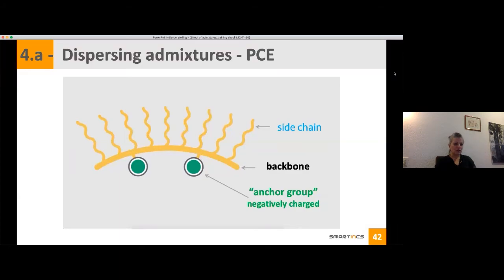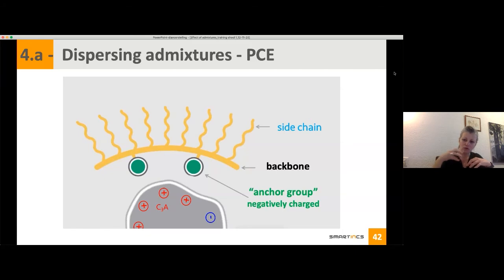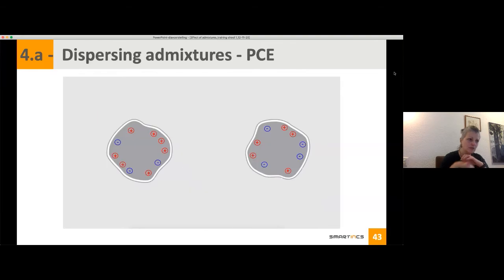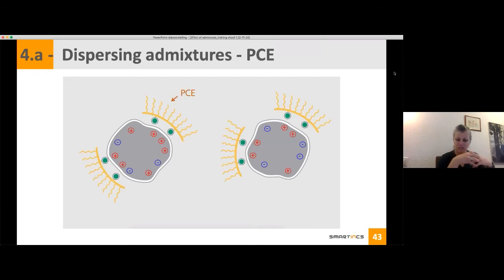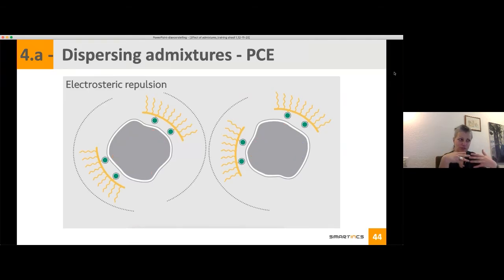So this is my PCE. If you remember in the beginning, I mentioned that the cement particles, the aluminates, are positively charged. And here you see that your PCE, your anchor group, is negatively charged. So what is going to happen? Your PCE will go look for your C3A, and this is how it's going to adsorb. So now if I still take my 2 cement particles, with positively and negatively charged areas, you have your PCE that is going to adsorb on the surface, which means you will create some dispersion.